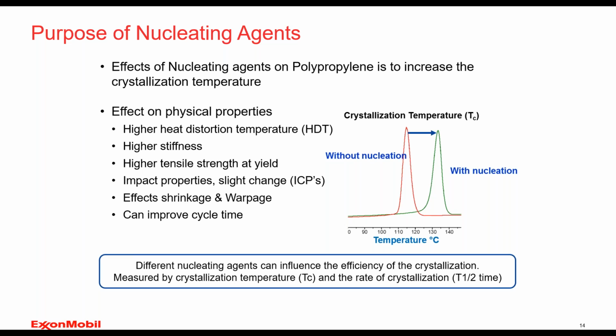And these dimensional aspects can be influenced by how the material is molded and how the shape or geometry of the finished part. And then ultimately, the biggest benefit to an injection molder is it can improve the cycle time and make for more efficient operations. If we look at the diagram here, essentially a nucleator is shifting that T sub C value by as much as 20 degrees, and that baseline without nucleation T sub C can change depending on the type of catalyst systems used, but essentially you're getting a 20-degree offset or improvement in T sub C values.